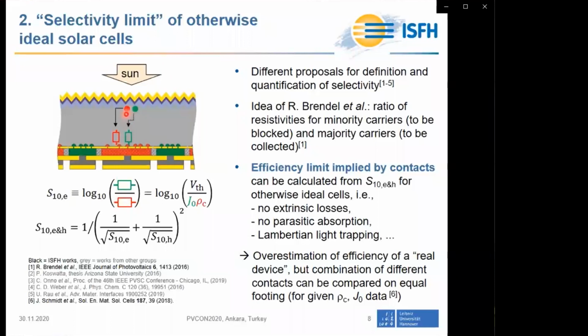Their resistance should be as large as possible, divided by the resistance for the majority carriers, which are in this case the electrons, and they should be collected effectively, and therefore their resistance should be as low as possible. And after doing some math, you can calculate that this definition comes down to the thermal voltage divided by the saturation current density for the recombination of minority carriers times the specific contact resistance for majority carriers.